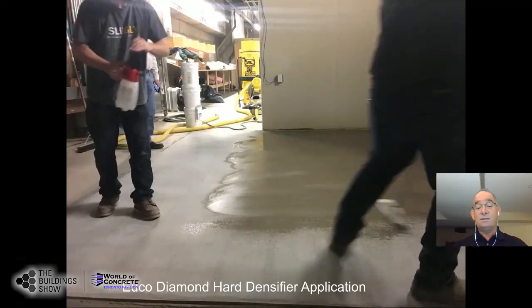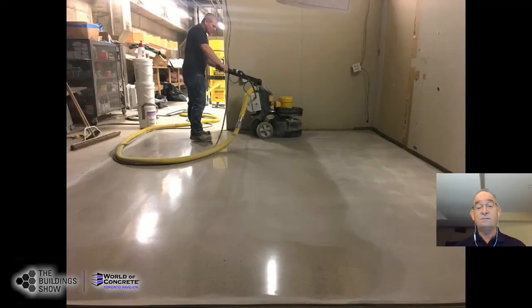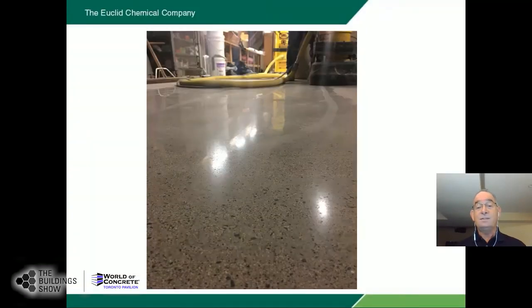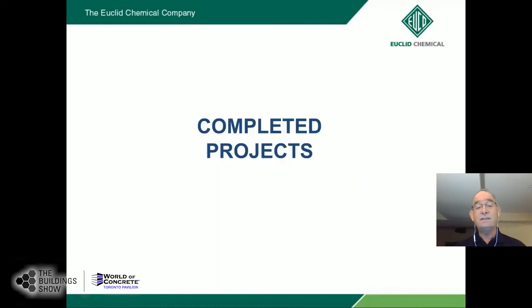Here we're applying the Diamond Hard Densifier, which is an integral part of all these overlayment materials. It's a densifier sealer, as I mentioned. So after the initial grinding process, all the debris is cleaned up, the dust and so on, and then it's treated with the Diamond Hard to help densify the surface, and then we carry on with the polishing process. And there's the end result. So quite a bit of steps involved in this, but that's why it takes a bit of time. But even having said that, we can generally get away with this in 3 or 4 days.